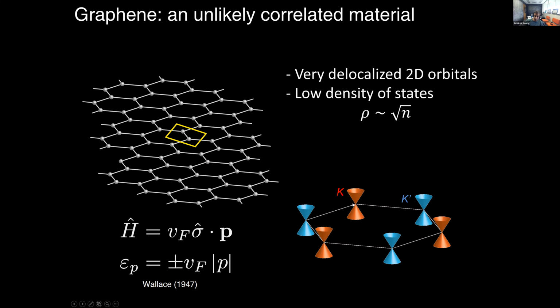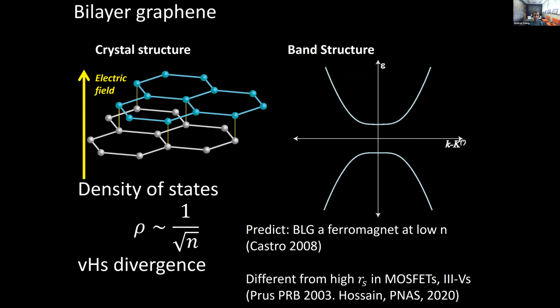So you can work through what the two-dimensional density of states is for this type of dispersion and find that it goes like square root n. It's very small, and that density of states is small, and you generally don't expect very strong correlated electron physics.